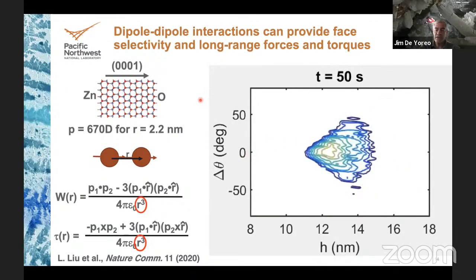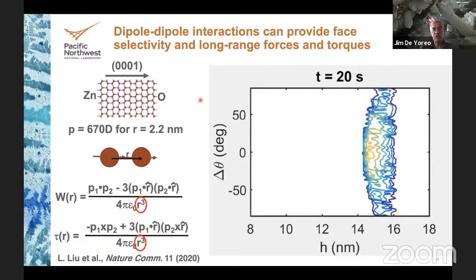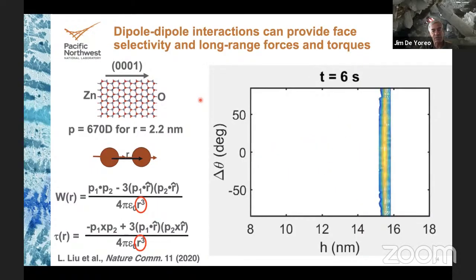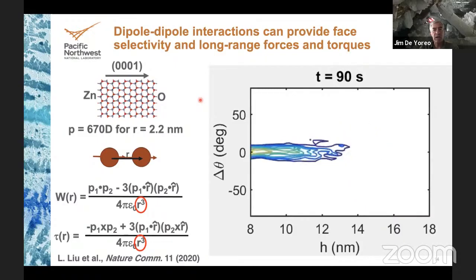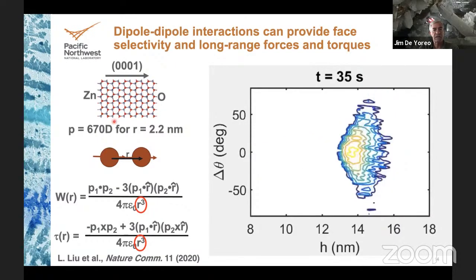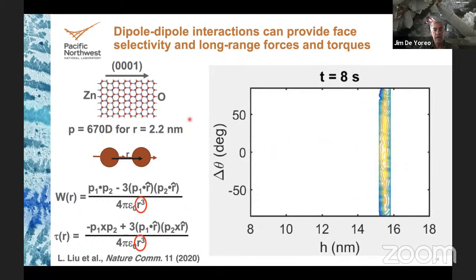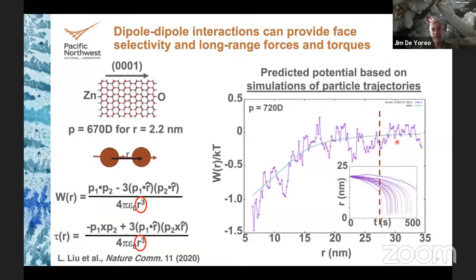Now, from these kinds of Langevin dynamic simulations, you can then produce a potential and compare it to the experimental data. And so the way he did that was to adjust the dipole moment so that the data matched the experiment at large distances. So the model simulations match the experiment.